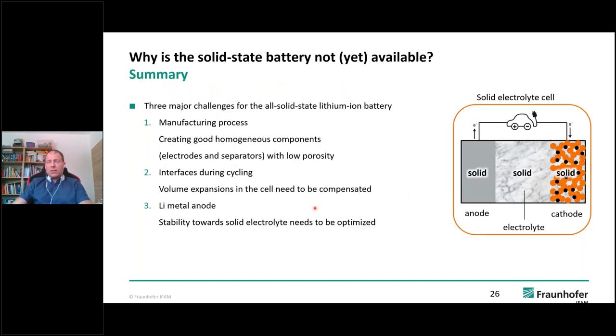So in summary, what are the major challenges for the solid state battery? The reason why it's not yet available is the manufacturing process, because we need homogeneous, non-porous components. We need good interfaces during cycling. By rebuilding the anode and having volume expansions inside of the cell, these need to be compensated one way or another, maybe by applying pressure on the cell. And then the lithium metal anode itself needs to be completely stable inside of the cell. So this is the problem.